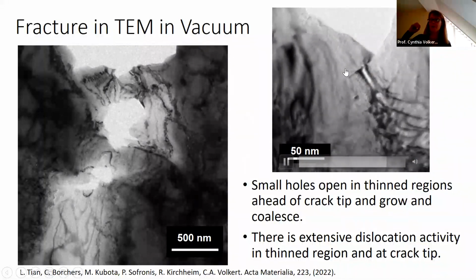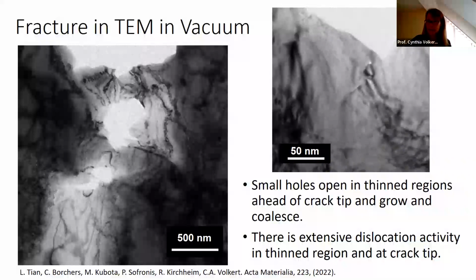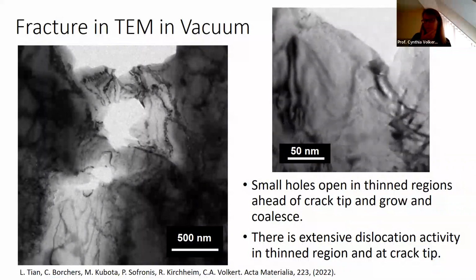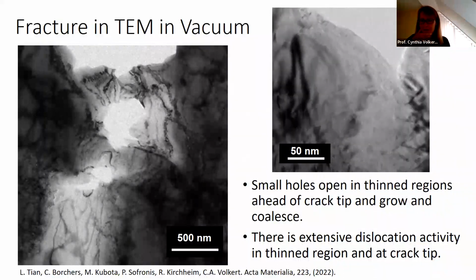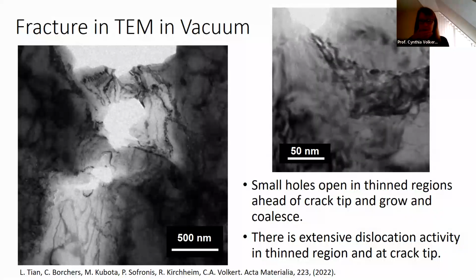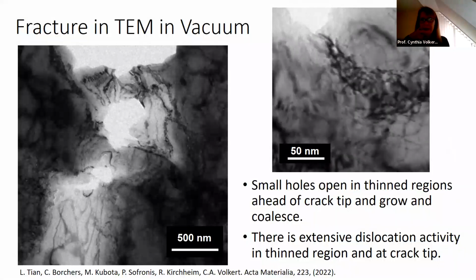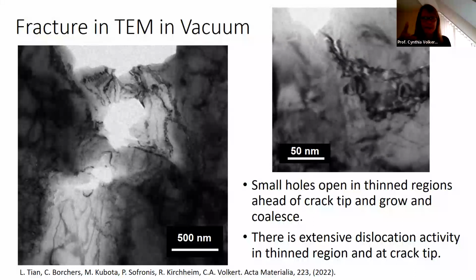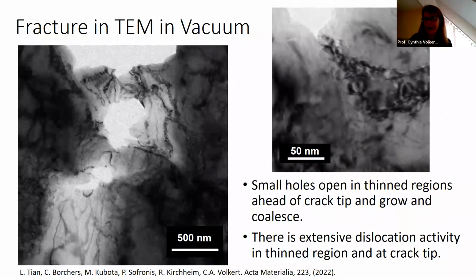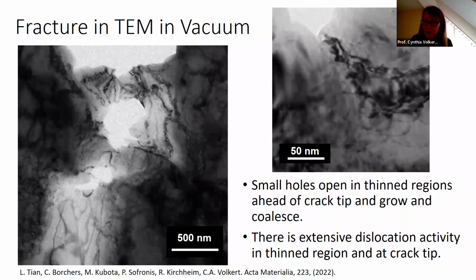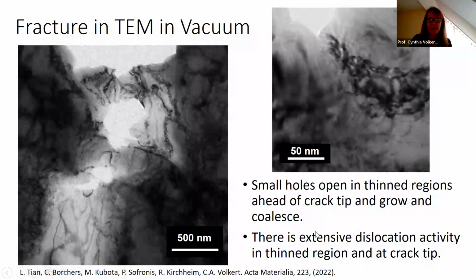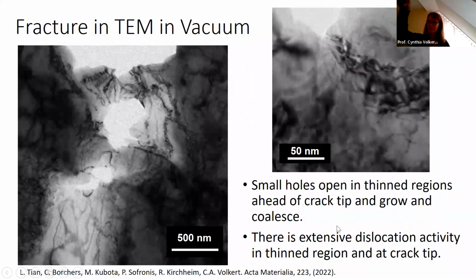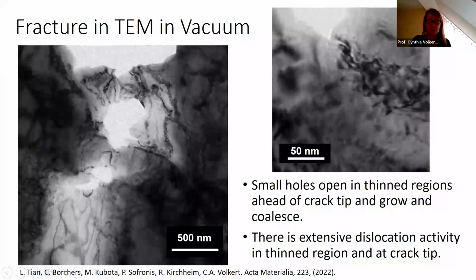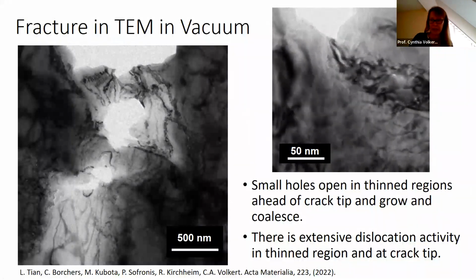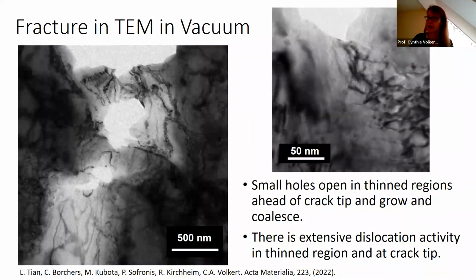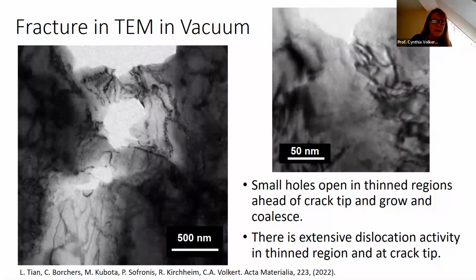During each test, the crack propagated through many grains. So each test involves a variety of different grain orientations and microstructures. And what we can say is that what I'm showing you here is characteristic of this behavior in the vacuum in the TEM. And so we see that the holes are nucleating ahead of the crack tip, and they join up and coalesce, and that's how the crack propagates.